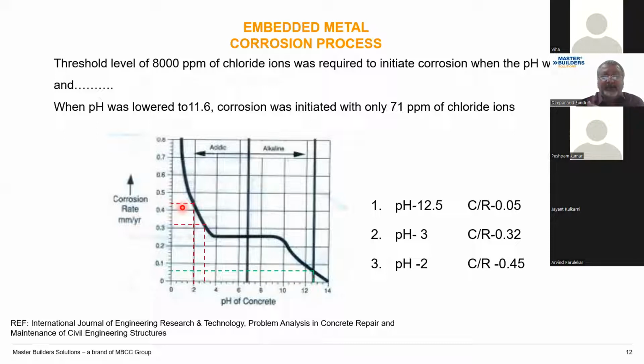So you can imagine if I have a 20 millimeter bar as a cover, which is exposed, and the pH of the concrete has gone down. Now, I'm not talking of the pH of the chemical that is being exposed, or don't think of a tank which has highly concentrated H2SO4 or HCl in it, at a very low pH. I'm talking of the pH of the concrete, which goes down, right? So when the pH of concrete is low, your corrosion rate is 0.45 millimeters per year.